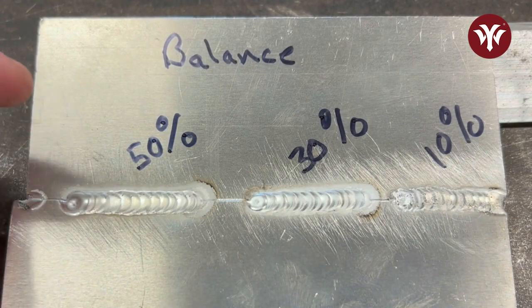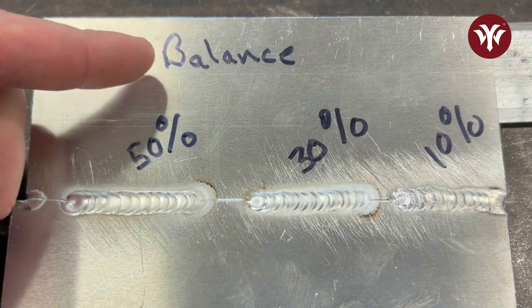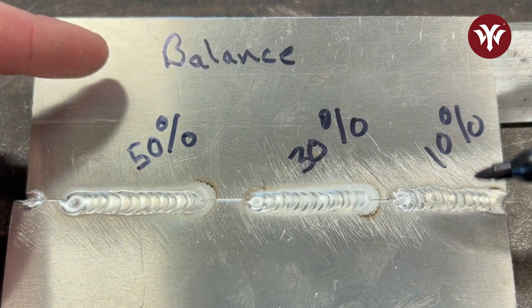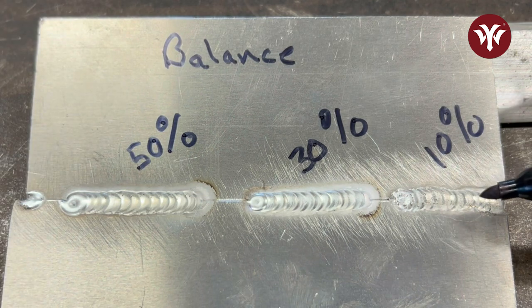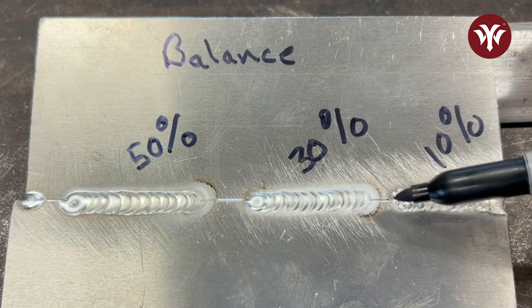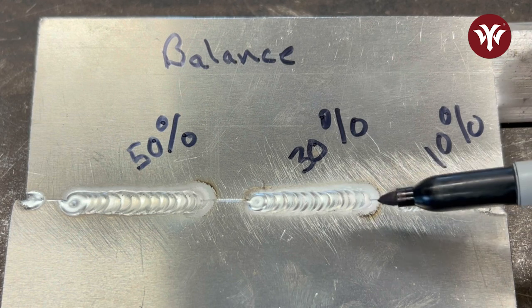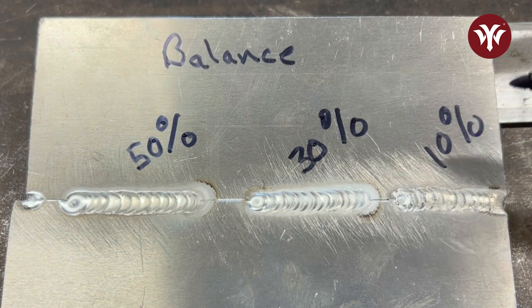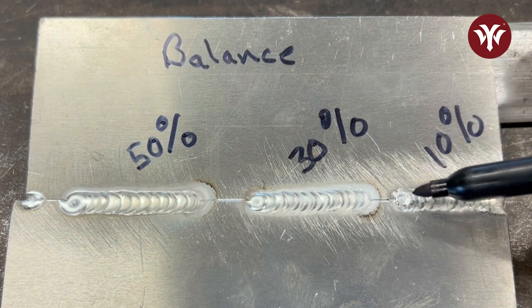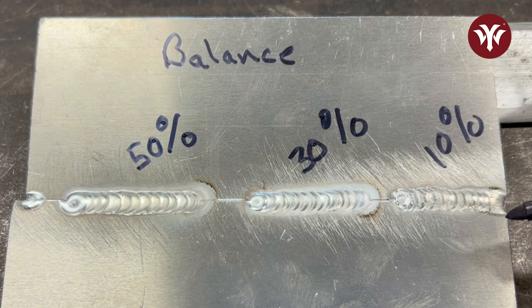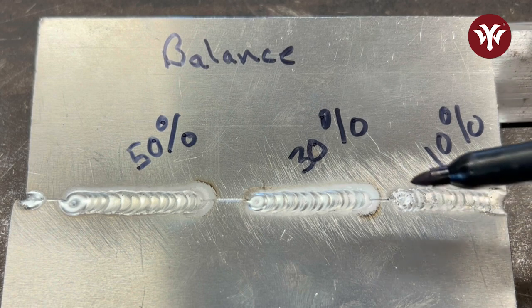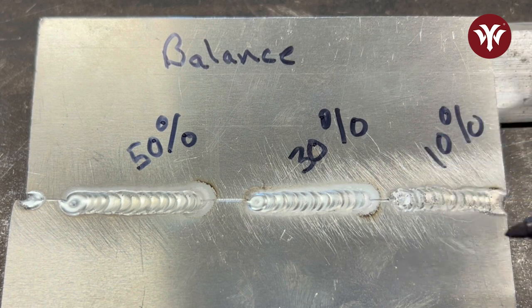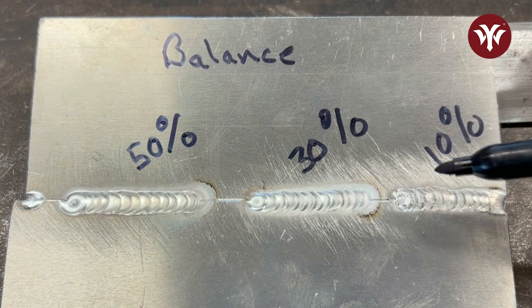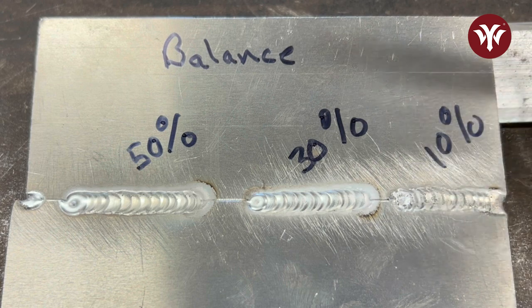All right, now that we got that first test done with the balance, let's take a look at the results here. As you can see, we're running with 10% balance, and that is not what I would be looking for. The etching zone around the weld is almost non-existent, which happens from cleaning on the positive half cycle. There's a lot of contaminants, as you can see, on top of the weld puddle itself, because they weren't getting removed, they were merely just floating up to the surface. So 10% with this material is too low for my liking, so I don't like that.